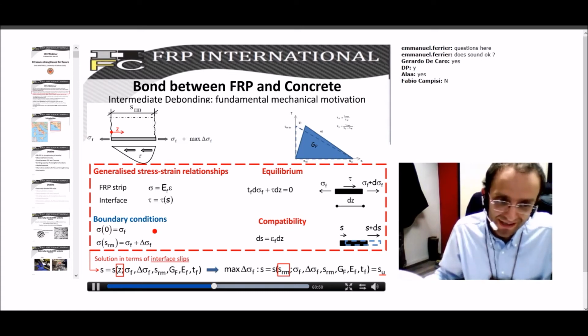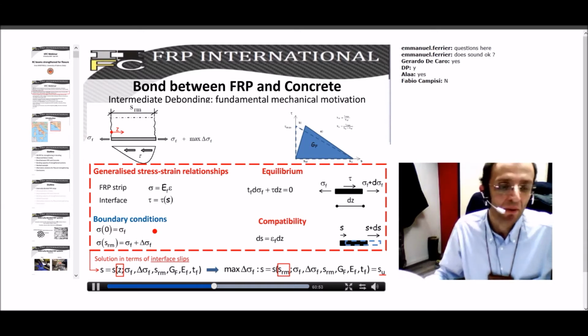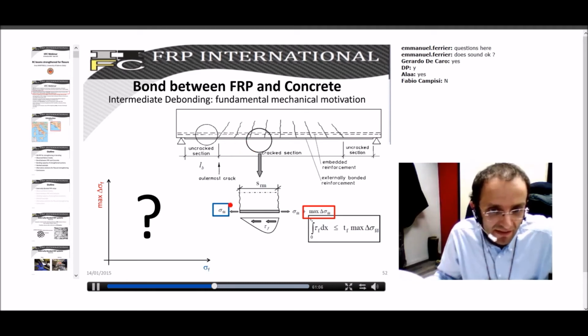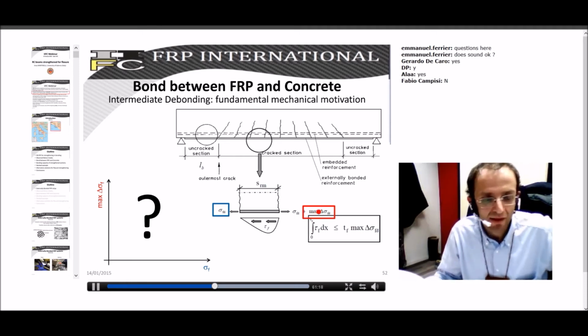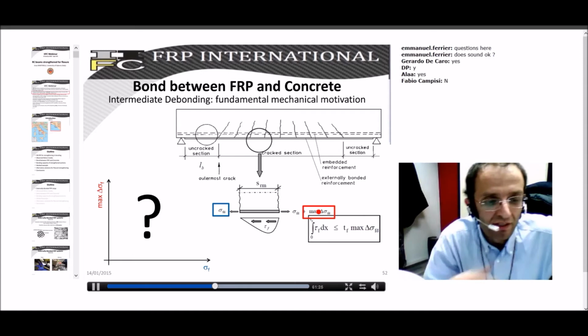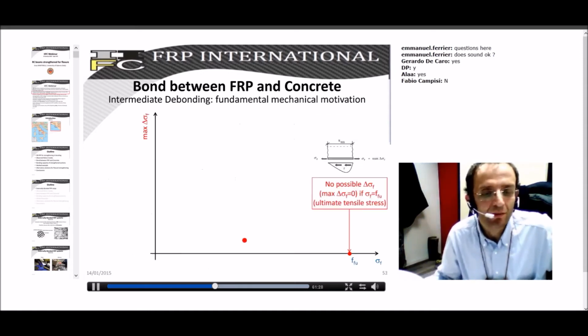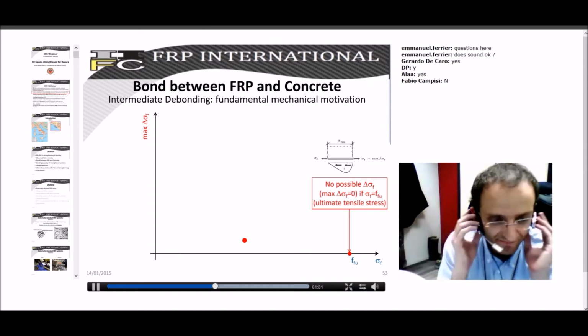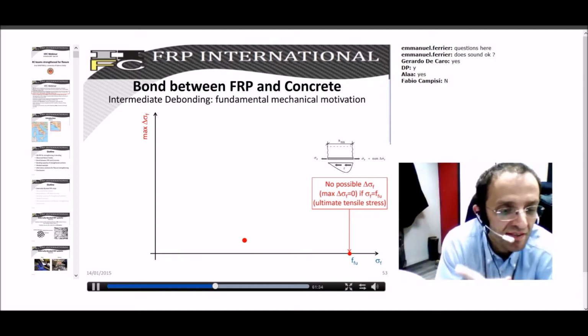The problem, as you can see, is rather complicated from the mathematical standpoint. It needs a numerical solution, but we can try to figure out what is the possible relationship between the applied sigma f, so the sigma f we have at the beginning of this segment, and the maximum delta sigma you have on the other side. The maximum delta sigma applied on the other side results in debonding for the glued FRP strip. So we can try to understand this, based on our physical intuition of the problem.